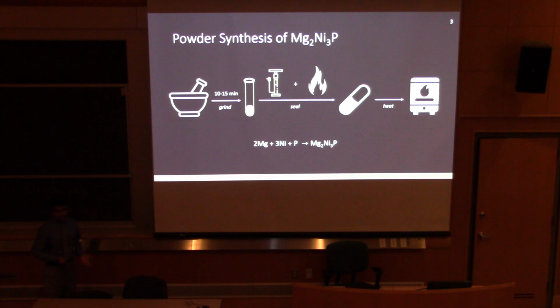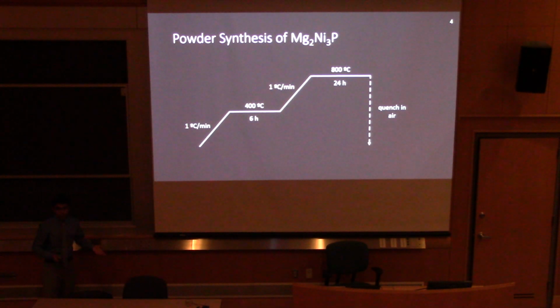And this heating cycle, I want to emphasize, is very trial and error. I've done maybe more than 40 samples at this point, and for each of these I've had to modify the temperature and so on and so forth. But for the purpose of time and simplicity, I want to just talk about two of these methods that I've used that yield the most promising results. Firstly, we ramp it up at a very slow rate, because if we ramp it up higher, phosphorus has a tendency to sublime, which means it goes from the solid state to the gaseous state. If it goes to the gaseous state very quickly, you can have pressure build up, once again causing the tube to explode, and you don't want explosions to happen. So if you heat it up very slowly, you allow enough time for pressure equilibrium, just allowing it to settle down.